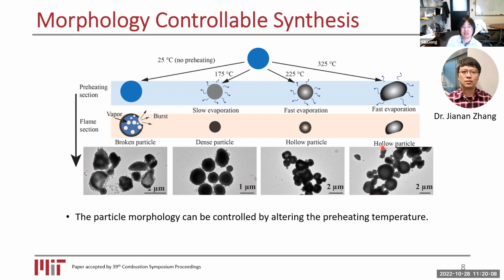So the way we did it was that we can control the temperature in the preheating section. So now this graph shows a sweep of temperatures starting from room temperature, no heating, to as high as 325 Celsius. And the bottom row demonstrates the TEM images of the end particles. And then you can see indeed the morphology changes a lot.